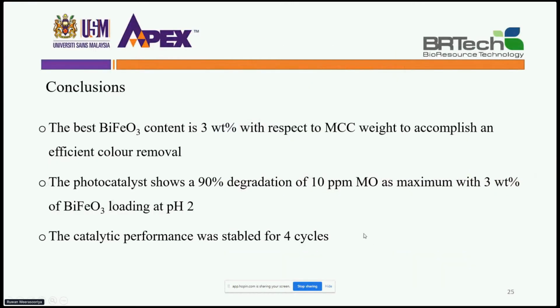So then the conclusion can be derived in this way. The identified best bismuth ferrite content is 3% with respect to MCC weight to accomplish an efficient color removal, and the maximum degradation is 90%. That was obtained with 10 ppm of methyl orange and 3% of bismuth ferrite loading at pH 2. So the catalytic performance was stable for 4 cycles.